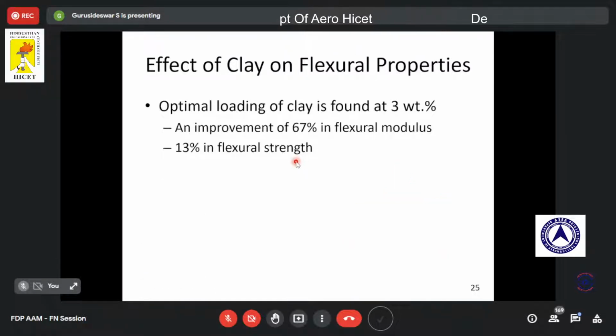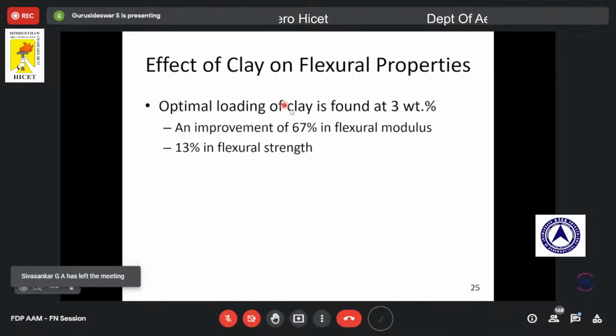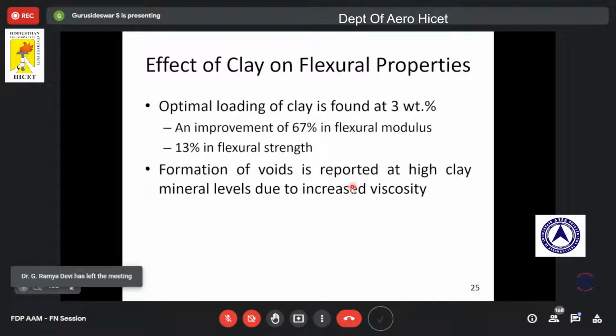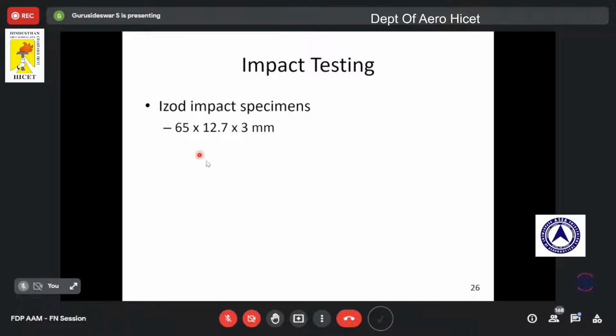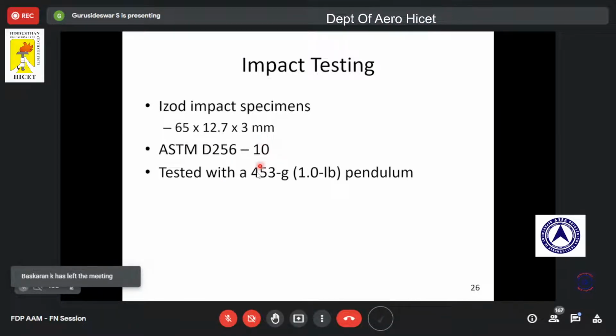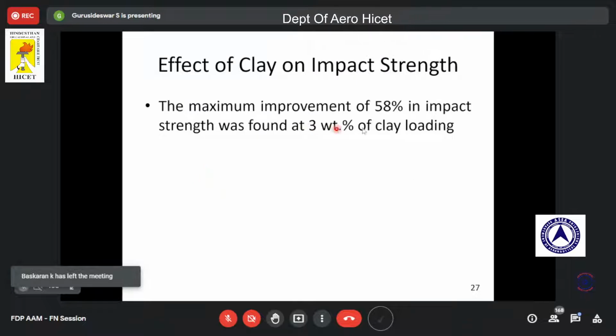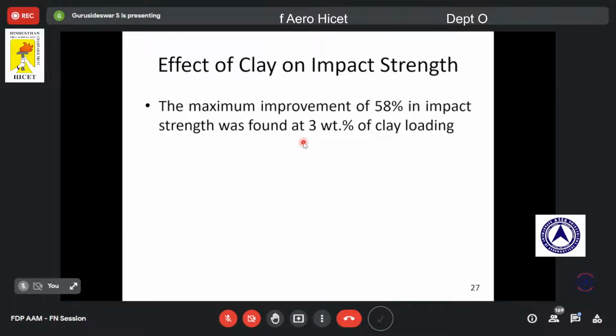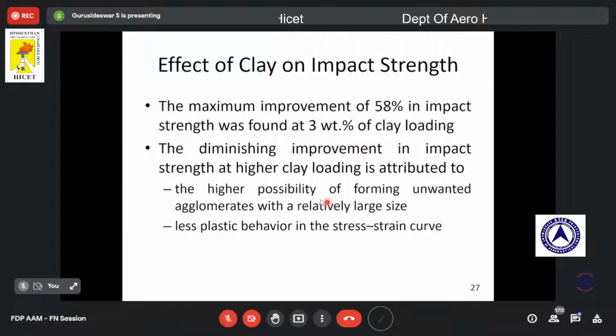So, the effect of clay on flexural properties. Again, similar to tensile properties, we have found improvement in flexure modulus by addition of clay, and also good improvement in flexure strength. But one drawback is we have found voids at higher clay content. These voids lead to premature failure. And then we have done impact testing as per ASTM standard D256. This is the sample dimension. Again, we have got good improvement in impact strength by addition of clay in epoxy. Again, as I told earlier, at higher clay loading, because of agglomeration and voids, we could not achieve good improvement for higher clay loading samples.